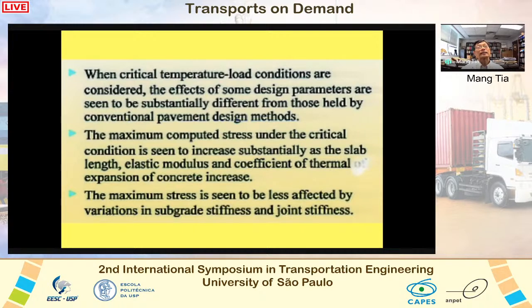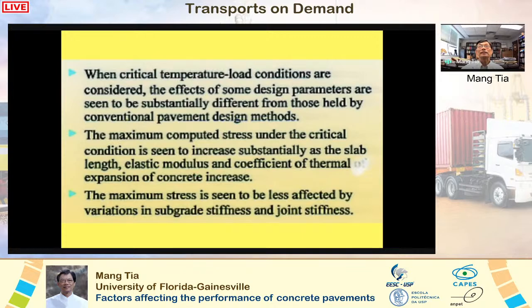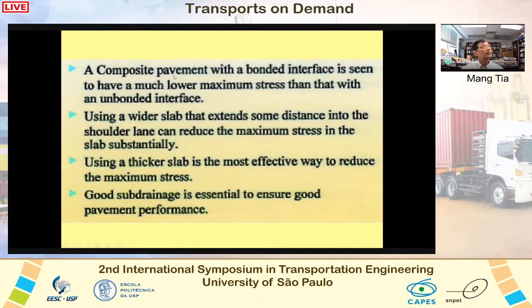We can make the following summarizing statements from our study. When critical temperature-load conditions are considered, the effects of some design parameters are seen to be substantially different from those held by conventional pavement design methods. The maximum computed stress under the critical condition is seen to increase substantially as the slab length, elastic modulus, and coefficient of thermal expansion of concrete increase. The maximum stress is seen to be less affected by variation in subgrade stiffness and joint stiffness. A composite pavement with a bonded interface is seen to have a much lower maximum stress than that with an unbonded interface.